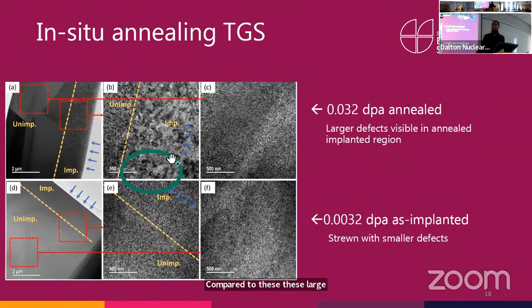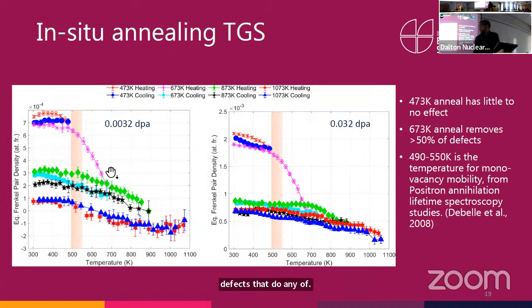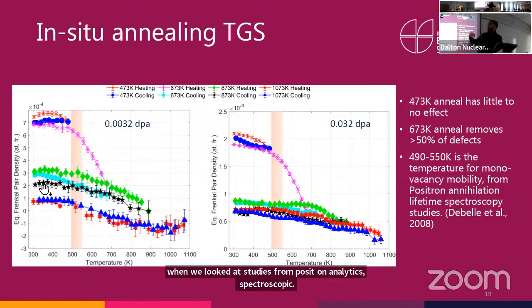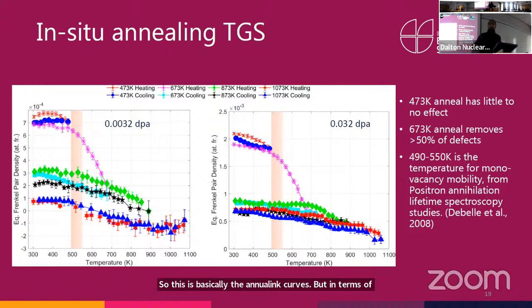And that led us to think that there are these larger defect structures that do not anneal off by 1073 Kelvin, and it's a lot of these small invisible defects that do anneal off. And when we looked at studies from positron annihilation spectroscopy, so this is basically the annealing curves, but in terms of the defect density, it said that monovacancies in tungsten become mobile in this temperature range of 500 to 600 Kelvin, which is leading to most of the recovery we see in our studies.